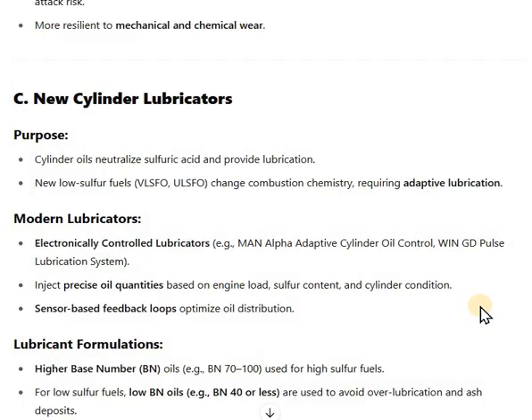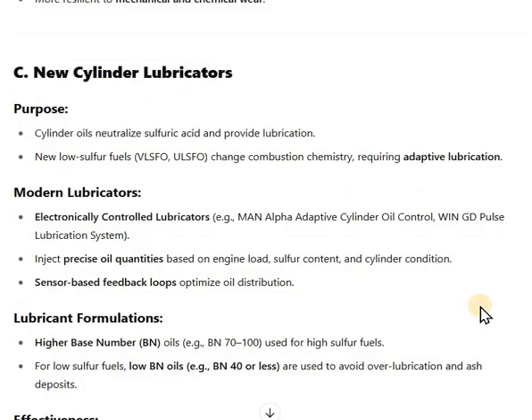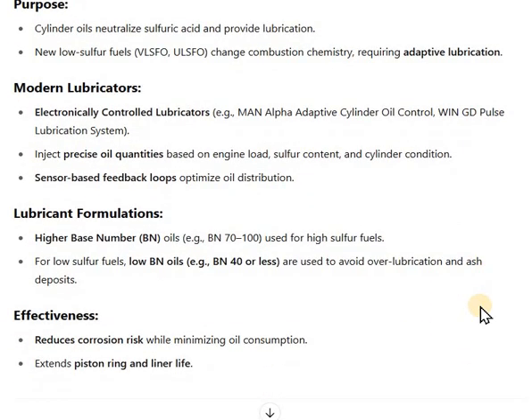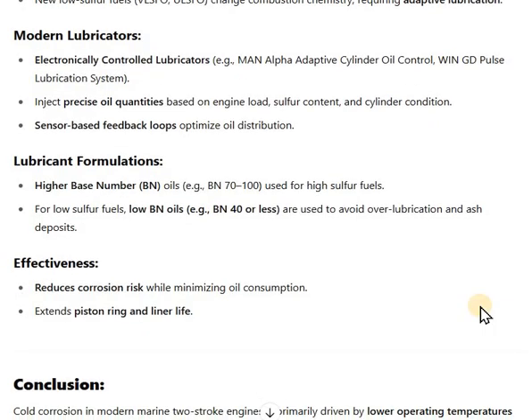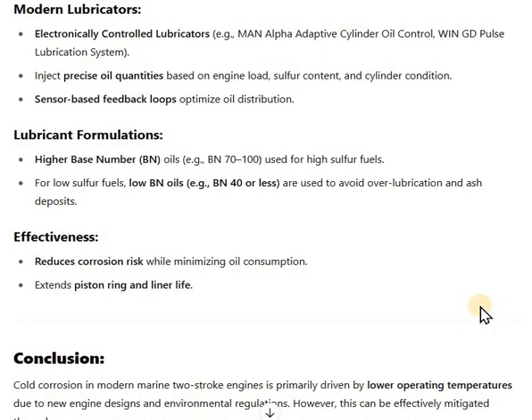Modern lubricators, electronically controlled lubricators, inject precise oil based on the engine load, sulfur content, and condition of the cylinder. Sensor based feedback loop optimizes oil distribution. Lubricant formulation: earlier it used to be a higher BN number, that is 70 to 100, used in higher sulfur fuels, and presently with the lower sulfur fuels, BN of 40 or less is effectively being used. So effectiveness: reduces corrosion risk while minimizing oil consumption, extends piston ring and liner life.